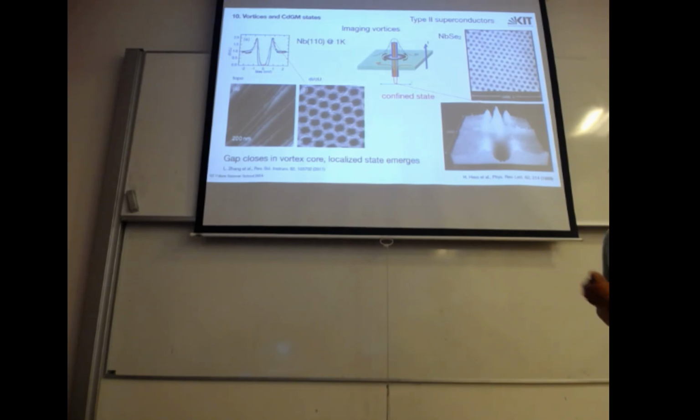And if we are on a vortex where the order parameter collapses, the material becomes simple, towards normal. This coherence peak will go down, our differential conductivity will go down, and we will see the vortex as dark. And this is what you see. You can actually map these vortices now with STM very nicely.